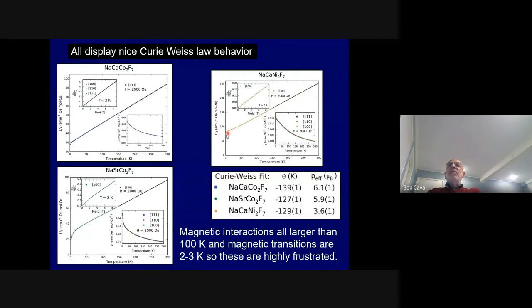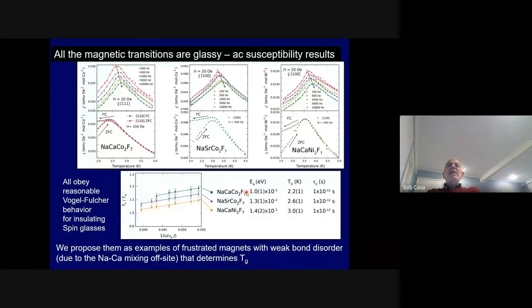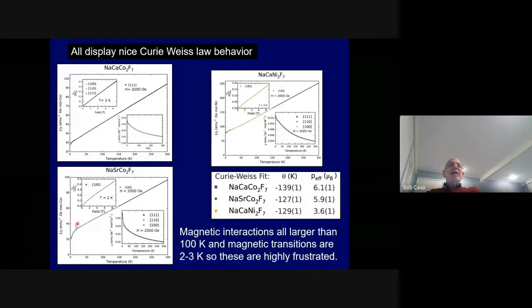So look at this one over here, this nickel one. Nickel is spin 1. So here you have spin 1 on a pyrochlore. Cobalt is really bizarre and wonderful, so we'll see more about cobalt later. But now what happened? So when you go all the way down here to around 2 or 3 Kelvin, they finally magnetically order. And what is that?